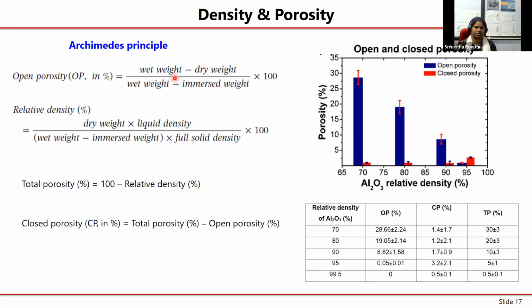And then after it is saturated, after all the liquid has gone into the pores, you can take it out, wipe all the lateral surfaces with a lint-free tissue paper, and then weigh again, that is the so-called wet weight. Using these 3 weights, one could measure the open porosity fraction in the material, as well as the relative density of the material. Once we know these 2 values, your total porosity is nothing but 100 minus your relative density. If I know total porosity and open porosity, then your closed porosity is nothing but total porosity minus open porosity. Okay. So using these expressions, I have quantified the open, closed and total porosity and relative density for all the specimens. And this is the trend.